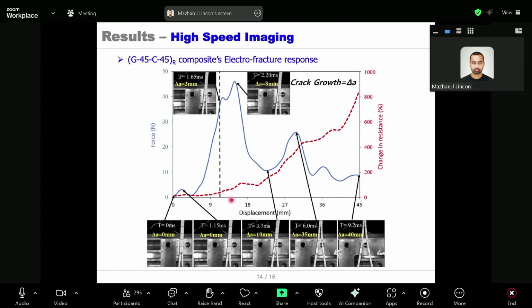Upon the application of opening, the specimen experienced a sharp increase of the force. Around time 1.65 milliseconds, crack initiation happens. Before crack initiation, the change in resistance is very minimal. But after crack initiation happens, the change in resistance increases gradually. And after that the force starts decreasing.